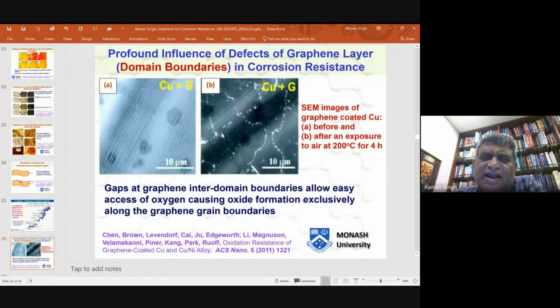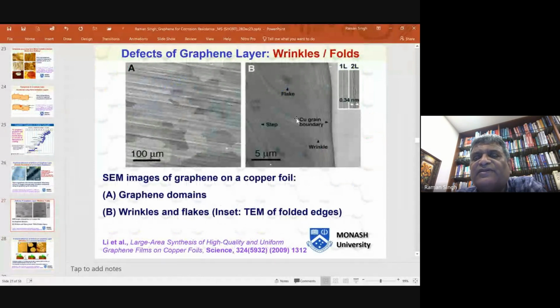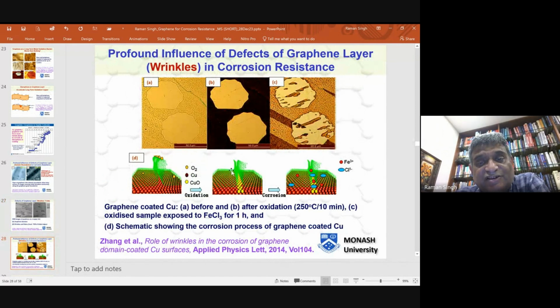Graphene has another problem. When it is developed by chemical vapor deposition on metal, it invariably has the problem of these boundaries. The first paper by Rod Ruoff, he also showed that there is corrosion at the boundary. He didn't mention it, but the micrograph clearly shows it. Graphene has another problem of wrinkles. Why? Because graphene is one of the rare materials which has negative coefficient of thermal expansion. What does this mean? That when you cool graphene, it expands, unlike other materials. So when you do chemical vapor deposition, the metal underneath contracts upon cooling, whereas graphene expands, and that leads to formation of more and more wrinkles. And those wrinkles are a problem, because at the top of the wrinkle there can be so much stress that it will crack, and corrosion can take place exactly at the wrinkles.